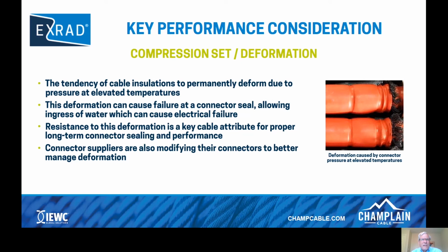Compression set is the tendency of a cable's insulation to permanently deform due to pressure at elevated temperatures. You can see here in the illustration on the right, this was a cable that had undergone temperature cycling, and you can see the deformation of the insulation. That deformation can cause a failure at a connector seal, allowing for the ingress of water, which can cause electrical failure.